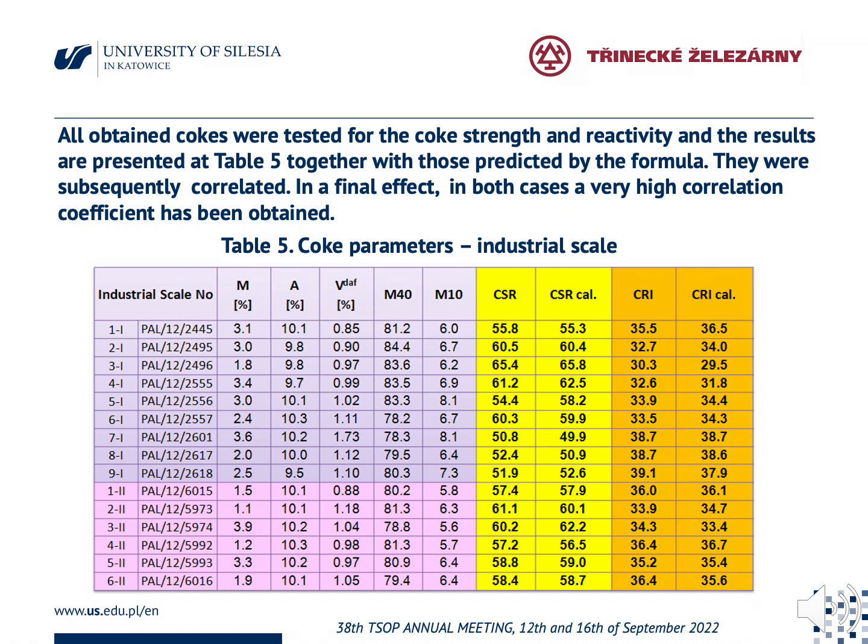The moisture content does not exceed 4%. Ash in a few cases slightly exceeds 10%, and volatile matter only in one case reaches a value approaching 2%. Both Micum results are fairly regular. Micum M40 oscillates around 80 and Micum M10 varies between 5.6 and 8.1. Attention is drawn to the CRI and CSR values obtained by test and compared with values calculated from the petrographic formula. Sum reactive was determined by the mean reflectance threshold plus or minus half a class of the mean reflectance values.